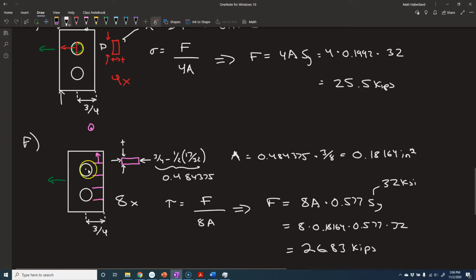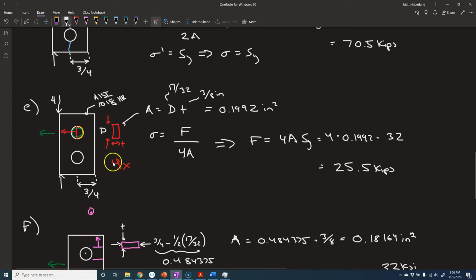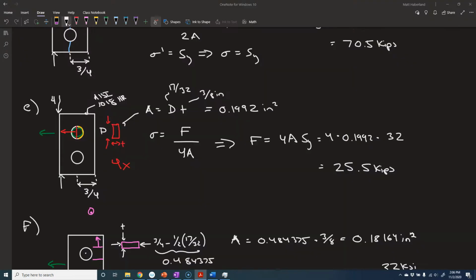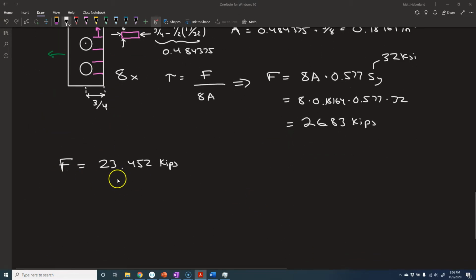But we had to check all the rest because it's conceivable that, if this distance were a little bit shorter between the center of the hole and the edge, or if the material weren't 1018 steel, if it were like SAE 1006, we'd have much less strength, right? So depending on those things, other parts of the joint could fail before the bolts. But it turns out the bolts fail first. They will yield at 23.452 kips.